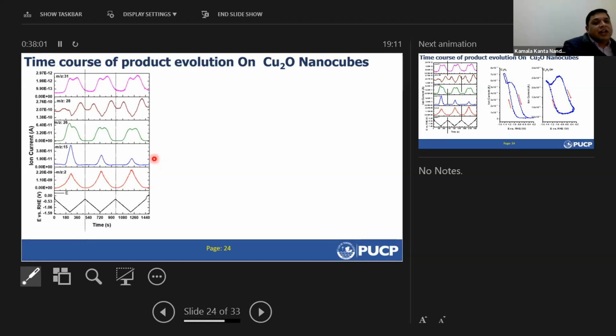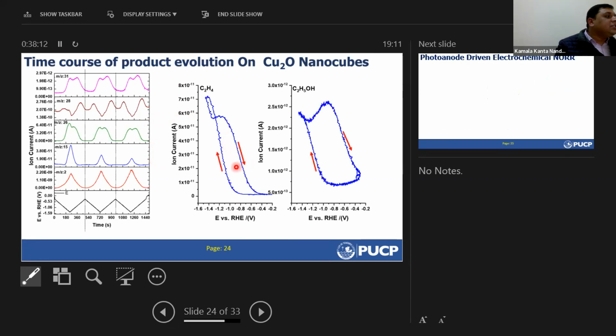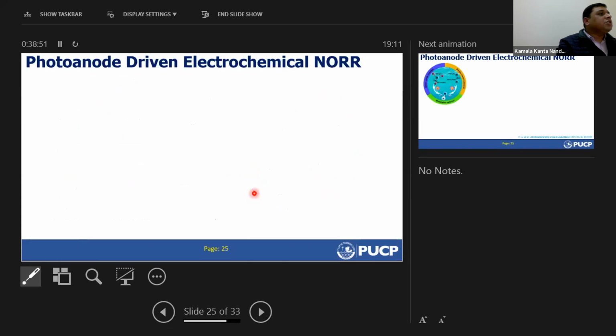From this study, we concluded that the copper 100 surface in Cu2O nanocubes is getting better with the passage of time during the electrocatalysis process. Further, we could find a hysteresis in the case of C2 products. There is no hysteresis in the case of hydrogen or C1 products. Hysteresis means your anodic sweep doesn't coincide with your cathodic sweep, and there is a little gap between them. That's a difference in onset potential. It is due to the adsorption of CO2 reduction intermediates, and you have a longer-lived intermediate in the case of ethanol than ethylene. So these are the conclusions we can obtain from the DEMS measurement, and it will direct us to get a new catalyst with a specific facet and specific ratio of the facet, which can give us a specific product.